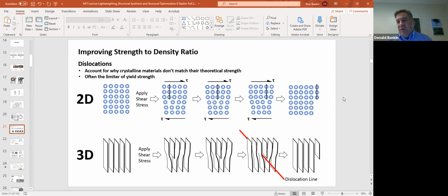You guys can pull a paper clip out of your backpack right now and bend it, and exactly what you're doing as you bend it is you're moving those dislocations around. In 3D, material scientists often talk about a dislocation as a line. If you think of a grain of material as a 3D lattice of atoms with this missing column, you can begin to think of all those columns lining up as a dislocation line. Believe it or not, if you measure the length of this line, there are several kilometers of dislocation line, even inside a grain that's maybe 10 microns or 100 microns wide. So there are many dislocations inside a grain of material.